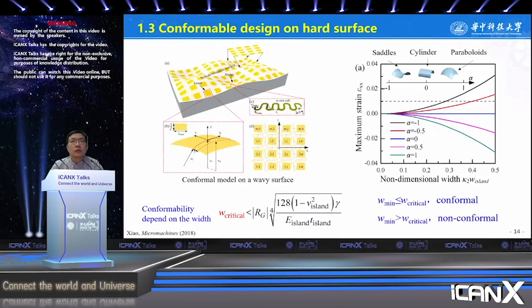Compared with the soft surface, the hard surface doesn't accommodate any elastic energy, making the electronics much easier to generate wrinkle and delamination. The left figure is the conformability of an island-bridge structure on a rigid, non-developable surface. The right figure shows the maximum strain in the island with non-dimensional width during conformable contact. The conformability depends on the width of the island. We also obtain the final critical width as shown in the red